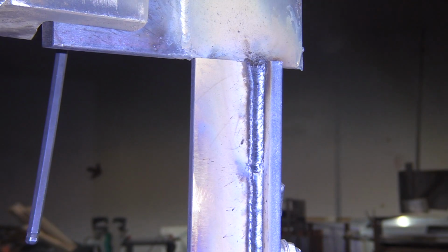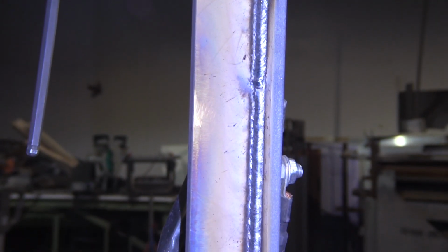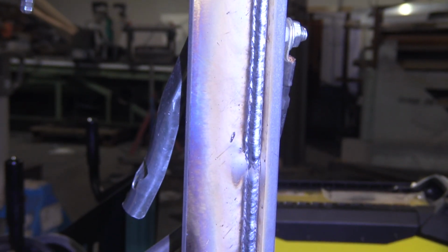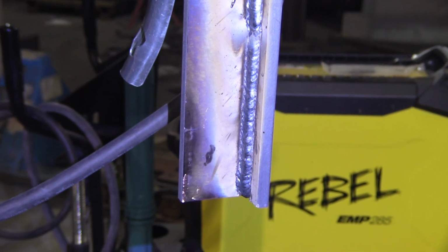Okay, almost done with the first pass. Not really experiencing any arc blow, and part of that is because we do have the amperage set down toward the lower end of the range with the arc force set at about 50%, which is a little bit higher than recommended for 7018, but it's working out. Andrew likes to weld them all the way to the end and then wrap the corner. All right, let's pan down here. There's one restart. Here's another restart. And they're not very visible at all.